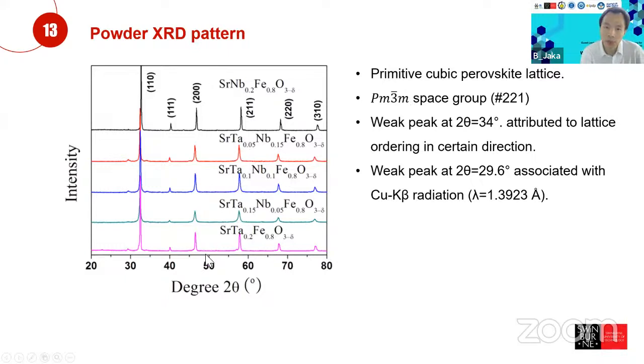correspond to the Pm3m space group. Of course, I have to say that we ignore a little bit of the impurity phase that is formed in here, as you can see a little bit in here. So we only focus on the big picture of this powder X-ray diffraction pattern. Okay, the weak peak at 34 degrees can be attributed to the lattice ordering, and then the weak peak at 29.6 is associated with the copper K beta radiation. So in this particular XRD, we are using copper K alpha, but it was not very pure, so there is still a little bit of the copper K beta radiation that manifests in the system.